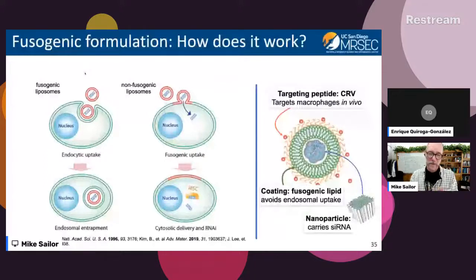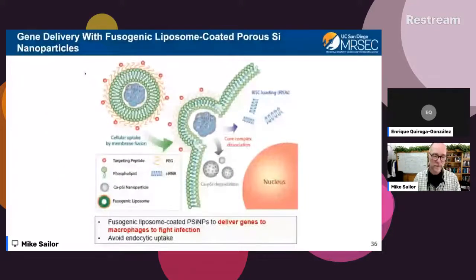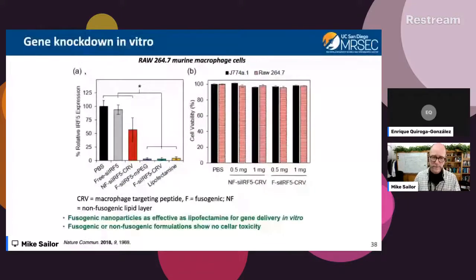In the end, what we're trying to do is what's shown in the center. We want this nanoparticle to hit the cell surface and dump its payload directly into the cytosol. And then the beauty of this is that with that protective coating gone, now our nanoparticle will dissolve very quickly and release its RNA payload. We found, in fact, this was very effective. So the basic concept is you have this targeted nanoparticle, it hits the cell surface, it fuses, it dumps its payload into the cytosol, the payload dissolves very quickly, and that nucleic acid therapeutic comes out where it can be very effective. I'll skip over some of this data considering the amount of time I have.